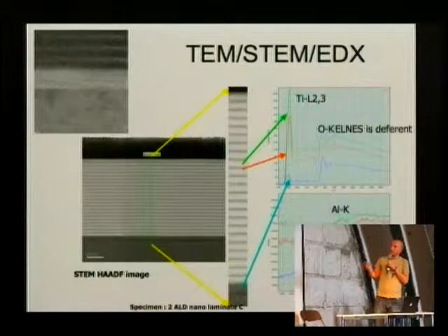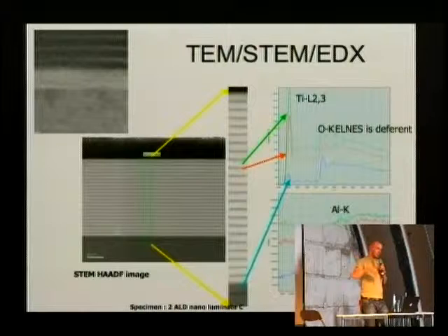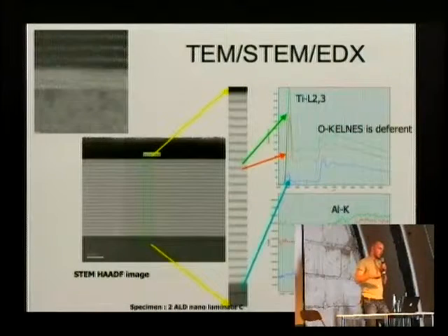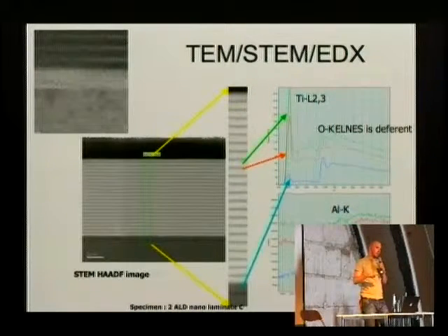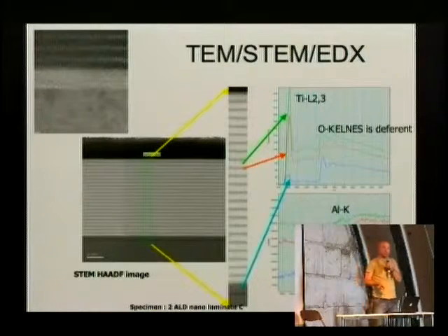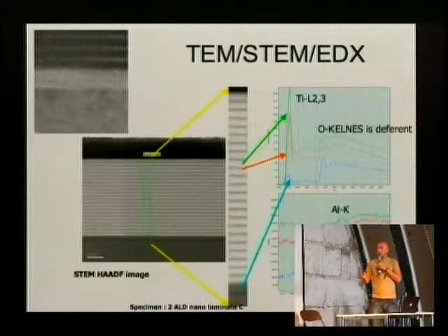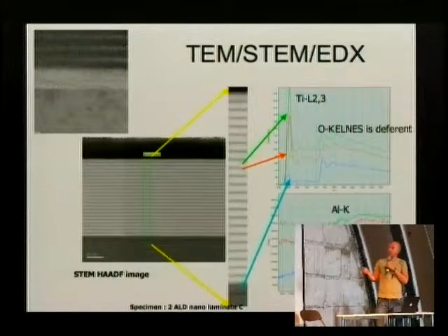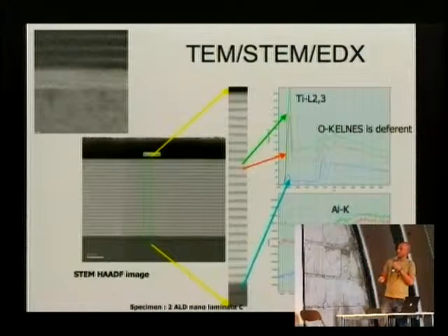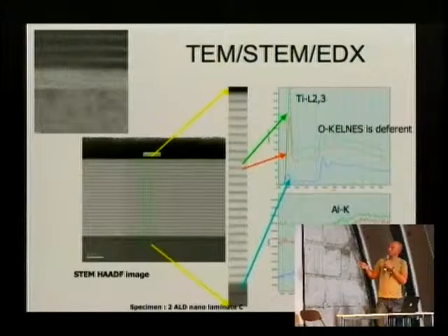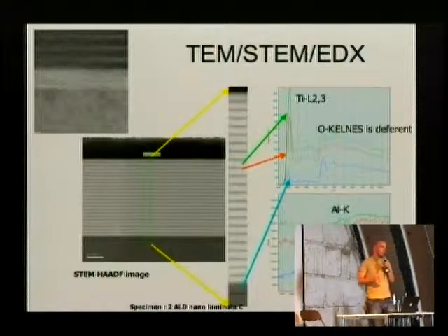So, as I told in the first slide, when you send electrons into a material, you not only get other electrons out or electrons flying through it, these electrons get decelerated, and decelerated charges create electromagnetic waves. So what happens is you have X-rays coming out of the material. So if you scan your beam very finely over this surface, for example here, there was a line scan taken, so the beam was moved over the surface, and some energy dispersive X-ray analysis was done. You get these curves, and what these curves tell you is what material is there.